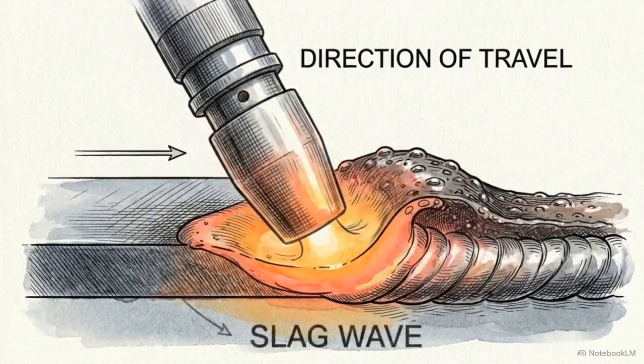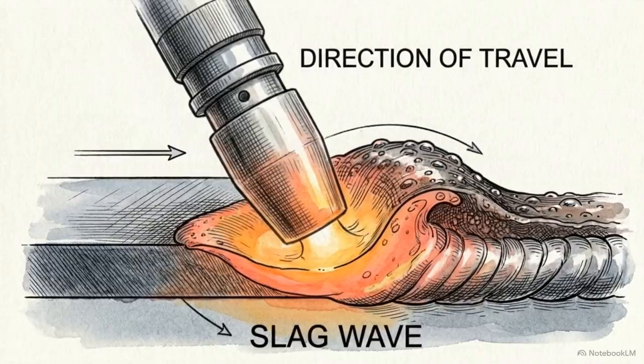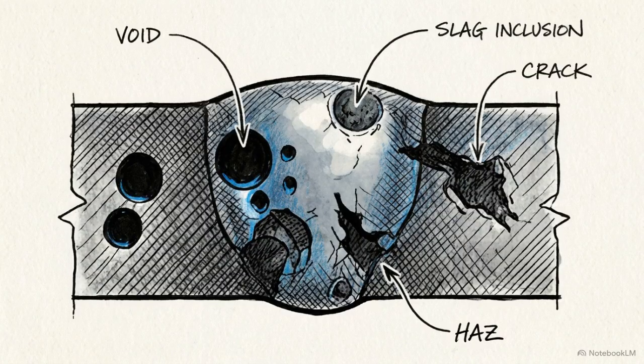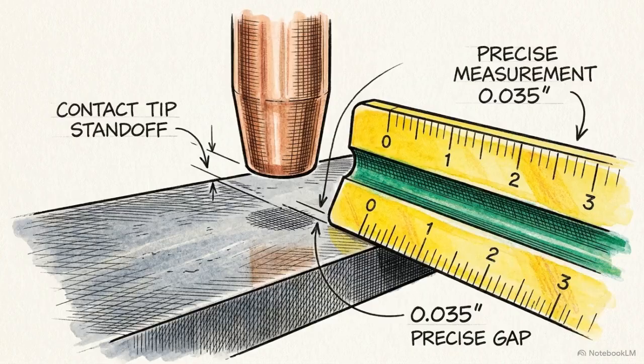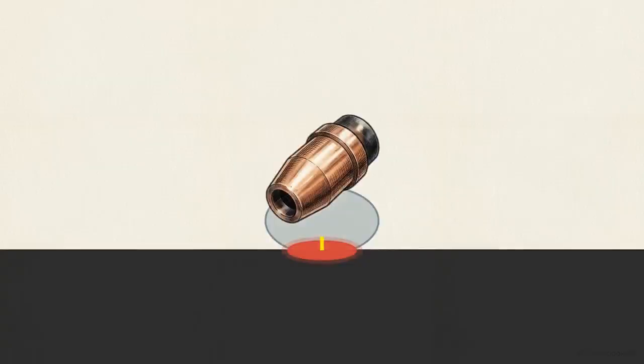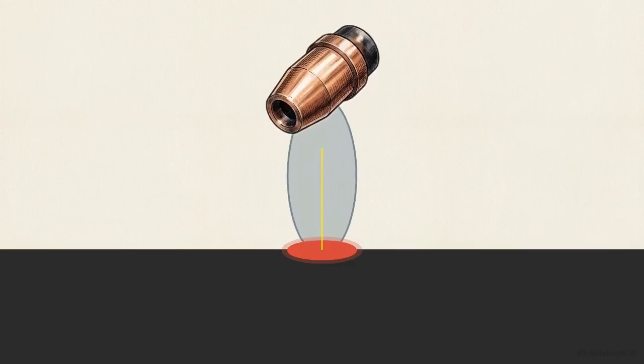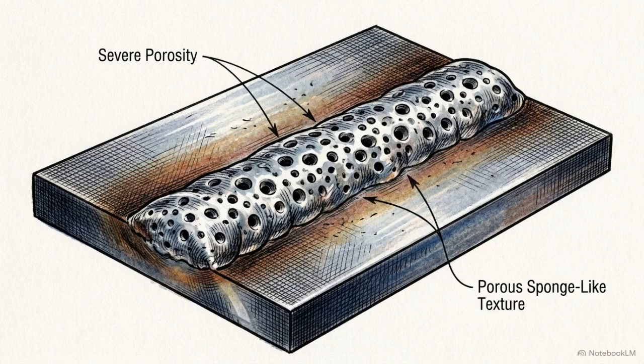If a welder uses a pushing technique instead of the required drag angle, they drive a wave of non-metallic slag forward, actively trapping voids inside the solidifying joint. Even the distance between the contact tip and the metal is heavily regulated. Holding the torch too far away stretches the arc and physically breaks the protective envelope of shielding gas. Without that shield, atmospheric nitrogen and oxygen instantly dissolve into the liquid steel, causing the surface to bubble with porosity.